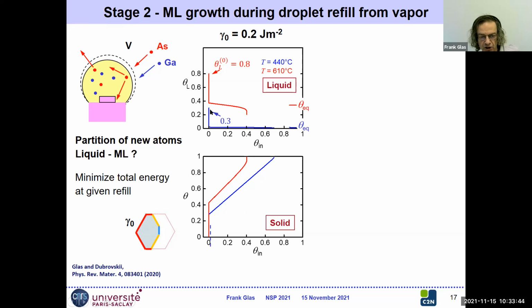low temperature, so I imagine that I had 0.3 monolayer of arsenic in the liquid. So I deplete the liquid, I use this, and you see that after this, it looks like a plateau. And this plateau in the liquid is very close to the arsenic concentration, which is the concentration of equilibrium of the liquid with the bulk gallium arsenide solid, which here is marked by this small bar here. So very simple picture. I deplete the liquid down to equilibrium more or less with the bulk solid gallium arsenide, and then during propagation, so this is the phase of propagation of the monolayer up to coverage equal 1, then I stay somewhere very close to equilibrium with bulk solid.